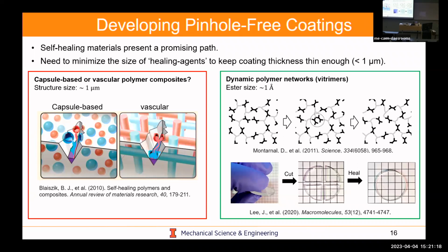One thing we liked was the fact that we could use dynamic polymer networks. These capsules are quite large, so the minimum size of these capsules is about 1 micron. You can't make them much smaller, it becomes very inefficient. But if you look at dynamic polymer networks or vitrimers, this is molecular length scale. So your ester size is about 1 angstrom. And so these are basically networks where you have dynamic exchange of bonding. And so this is work by Lee, where you could actually take these materials, cut them, and then just by pressing them together and applying a bit of heat, they actually fully recover, right? You don't see any more interfaces because of the cut. And so this is the approach we took.